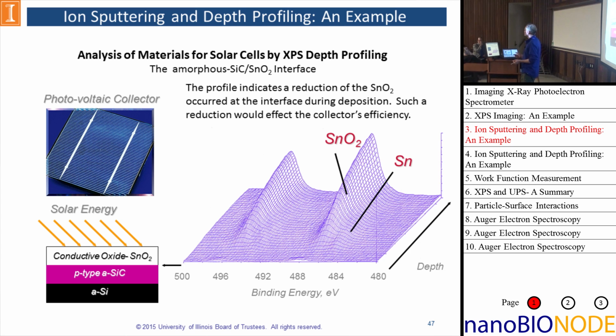Tim showed some really beautiful models of how that looks. And so in most cases, if you were to sputter a metal oxide, due to preferential removal of the oxygen, the metal reduces. But in this case, this group wanted to study the interface of the amorphous silicon carbide layer that's on top of the transparent tin oxide layer, to look for any evidence of reduction at this interface. And such reduction would affect the transparency at the interface and affect the photovoltaic efficiency.